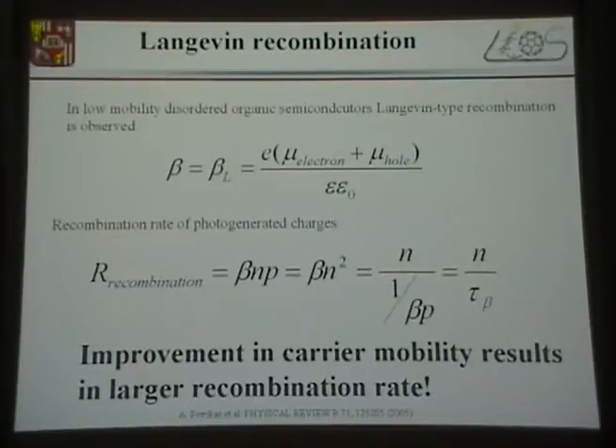To my understanding, the separation of the charge carriers goes hand in hand with recombination. So if we're able to split the exciton or exciplex or charge transfer state, why would they recombine again? And the way of understanding the recombination is, as you see here, the recombination rate equation, where you have a bimolecular recombination coefficient beta, and usually it's assumed to be of Langevin type, which means that the recombination coefficient is directly proportional to carrier mobility.